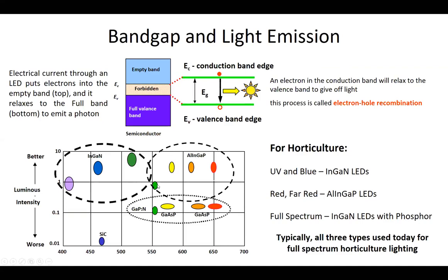The efficiency is not very good because this material system cannot make high efficiency green, can't make blue, can't make UV light emitting diodes at all. These LEDs down over here are all low brightness indicator die. In the 1970s, the very first gallium nitride light emitting diodes were made at RCA Research Labs outside of Princeton, New Jersey. They were not very bright. They were not easy to make. A lot of the world gave up on them for a while until the early 1990s.